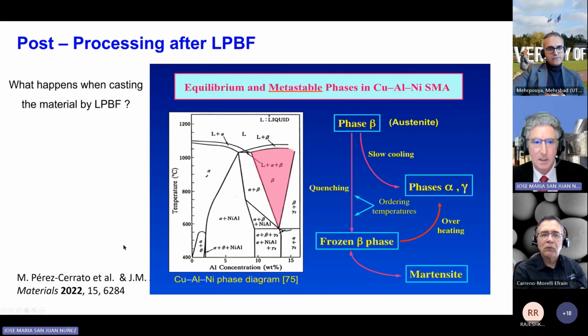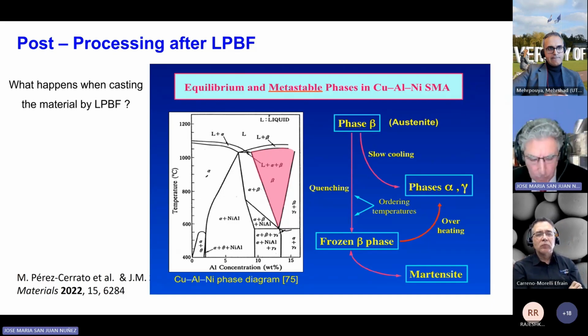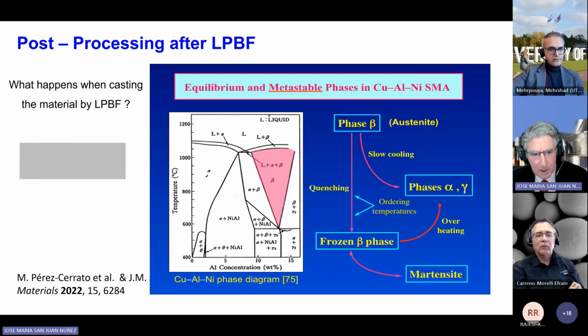So what happens when casting the material by laser powder bed fusion? We can imagine that when we are building our material layer by layer, the heat of the melting pool is released on the material very fast because of the high thermal conductivity. But what is happening, in fact, is that when we scan the laser and we melt, and the melt pool is scanned along the surface, there is some overheating of several layers beneath the melting pool. And this is repeated again if we melt another layer above.